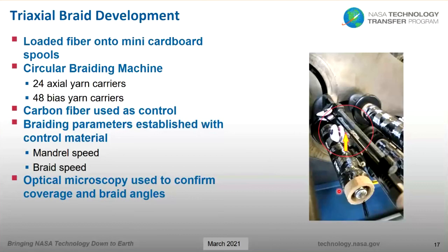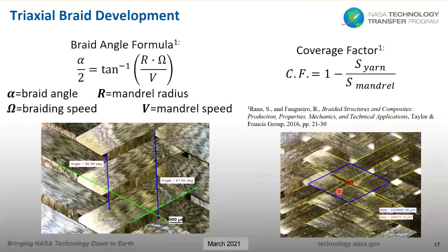Carbon fiber was also used as a control braid because it helped us to define the braiding parameters that we used, such as what is the right mandrel speed to use and what is the right braid speed to use. After braiding, we followed up with optical microscopy to help us confirm the coverage and the braid angles. When braiding, you can find the braid angle and coverage factors using the equations on this slide, where the braid angle takes into account the mandrel radius and the braid and mandrel speeds. The coverage factor is basically the amount of fiber coverage that you will get in your braid.